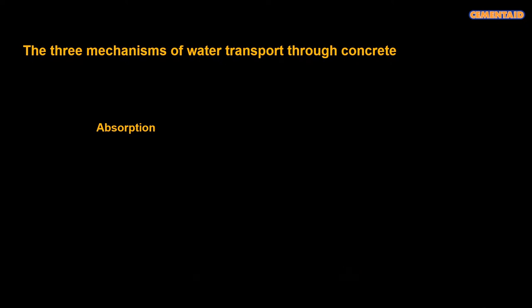That's a pretty straightforward test that you do on concrete. The standard test is detailed in BS 1881 part 122, where you just take a sample of concrete, dry it and immerse it in water, usually for a period of 30 minutes, and take it out and re-weigh it, and you measure the amount of absorption, the weight gain.